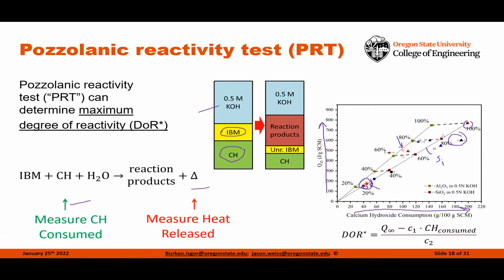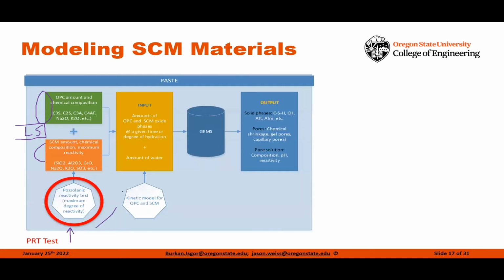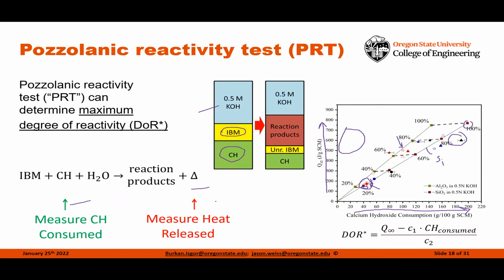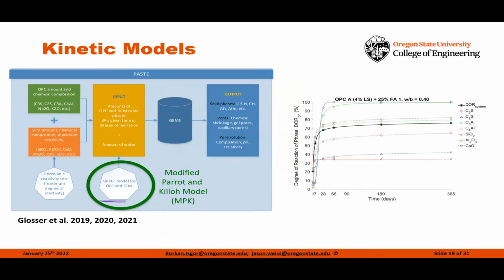And while we've shown here alumina and silica systems, we can also do the same thing for things like slags that fall into this category over here, where we can describe exactly the role that calcium plays in that system. So we can now come up with a numerical value for how reactive these different SCMs are. All of a sudden we can start describing these in a way that is, we believe, much more telling than something like a strength activity index, because we're actually measuring the reactivity and it drives the entire modeling of the system that we're looking at. In addition to that, we're also going to have to bring in some of the kinetic factors.